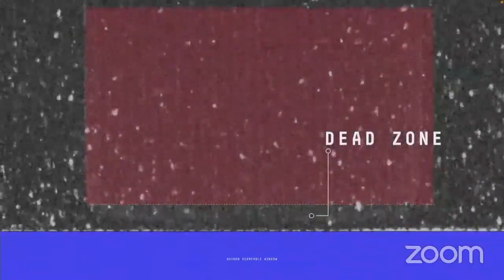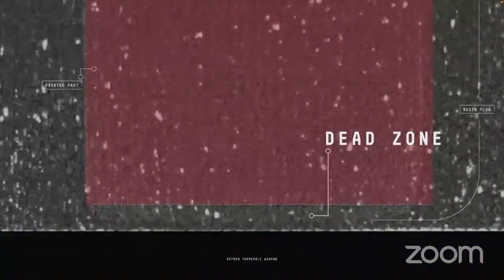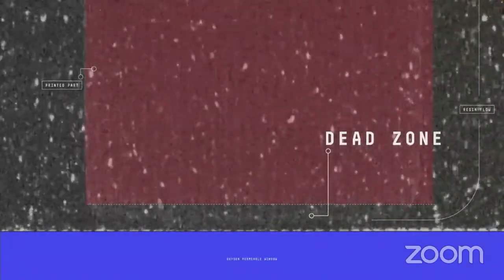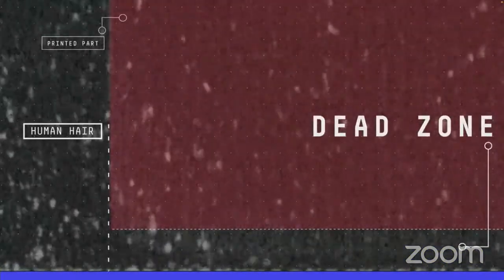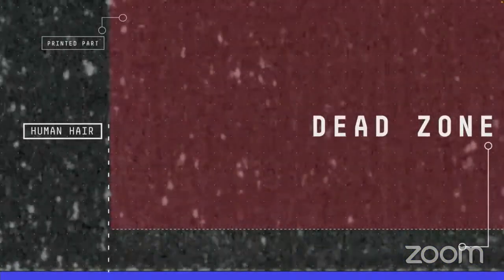This is optical coherence tomography, kind of like ultrasound imaging, but it uses light instead of sound waves. And you'll see the part growing. We put some particles in there as a contrast agent. But you can see this gap. This is a gap created by the oxygen. Light's coming through here, curing the resin, and as you lift the part up, resin's being drawn in underneath here.